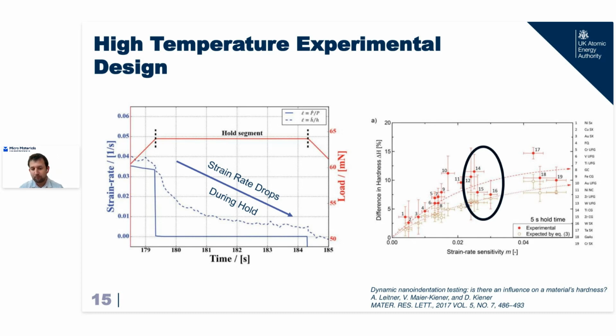Things like iron or coarse grain zinc, titanium, these are all in this circled bit, this middling strain rate sensitivity. And these can lead to errors in this 5-second hold period of up to 10%, which is quite significant for such a short hold period at room temperature. You can expect that uncertainty in your hardness measurement to be increasing even more once you're up at very high temperatures where these creep rates are significant.